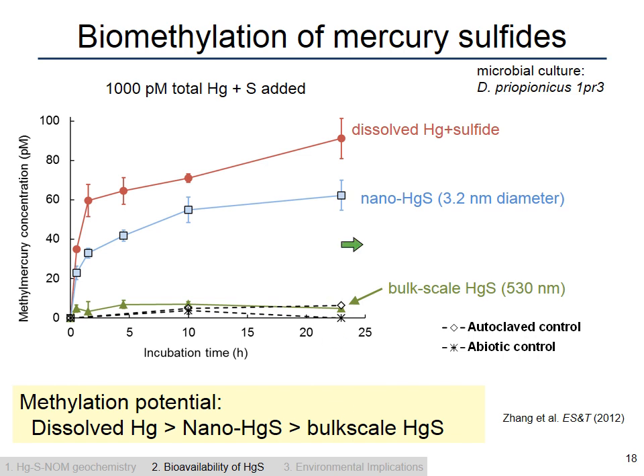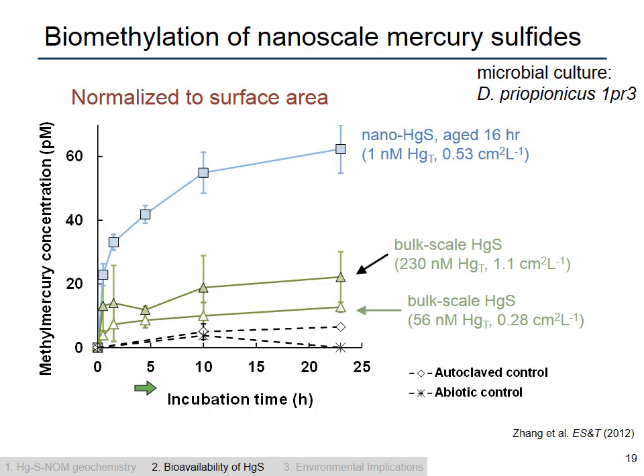You could argue that, well, the nanoparticles are smaller and they just have more surface area to release dissolved mercury compared to the big particles. So we redid this experiment where instead of normalizing to the same mercury concentration, we tried to normalize it to the same surface area of particles. So here we have nanoscale mercury sulfide at 1 nanomolar, and that amount of surface area added to the culture media. And we have bulk scale mercury sulfide added at two different concentrations, but similar surface area relative to the nanoparticles. And we can see that even when you try to normalize it to the surface area, the nanoparticles have an enhanced bioavailability. There's more methylmercury produced here for the nanoparticles as compared to the bulk scale particles.